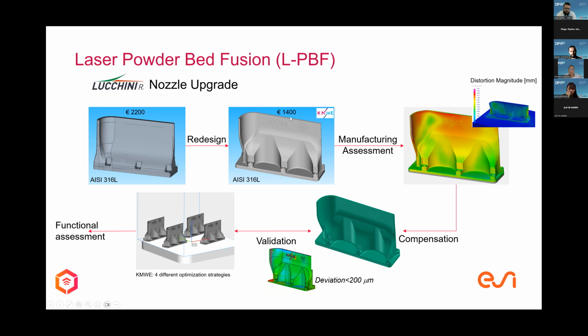We assess the cost. Then we assess the manufacturing process. Here we're looking at the distortion. The distortion was found to be fairly large, so it was compensated for. And we get a new geometry, not exactly that what was designed. It's a new geometry which has to be printed. But when it is printed, it moves, it deviates from its intended shape to achieve the shape which the designer wanted. And the deviation is below 200 micrometers, which is quite accurate, or that's what we considered for this part.